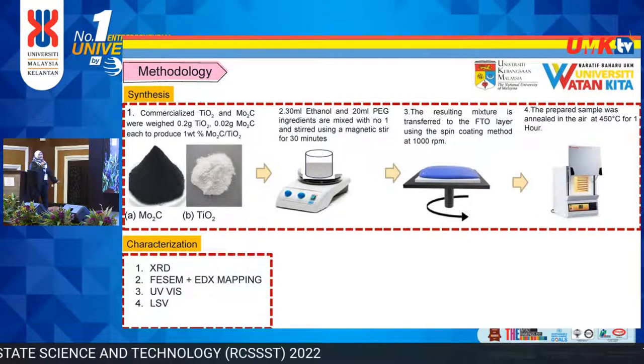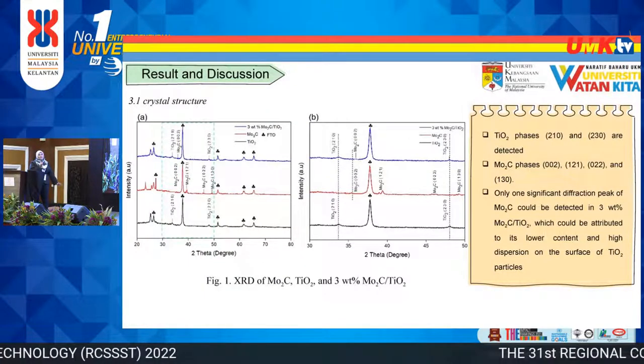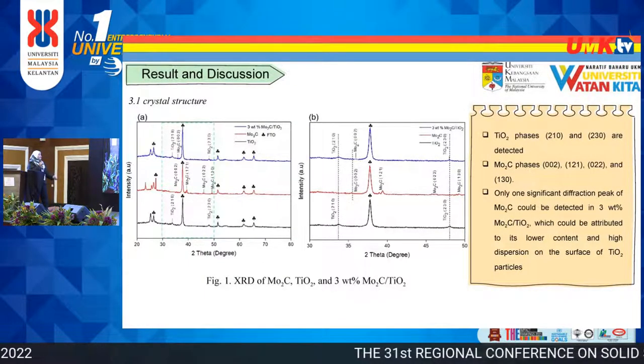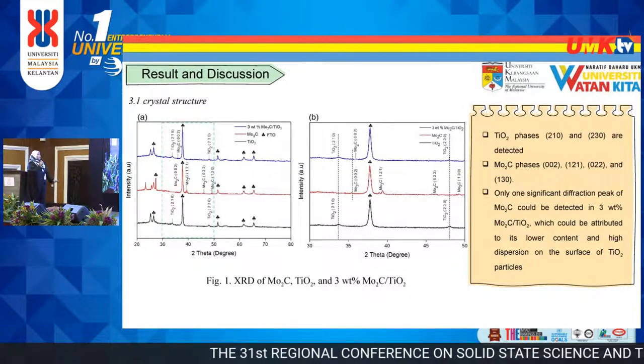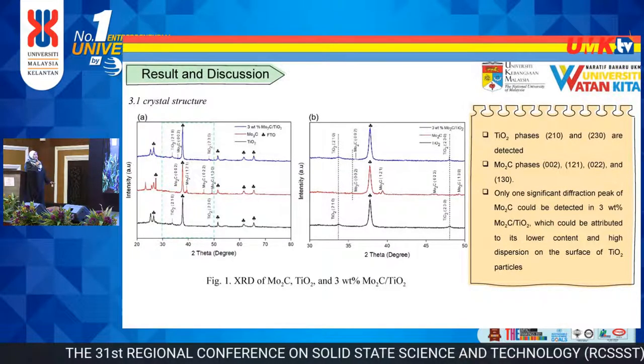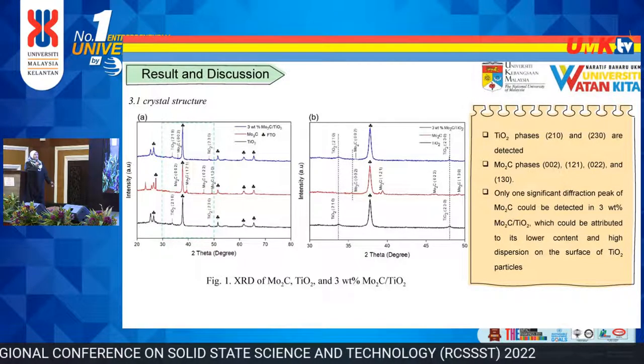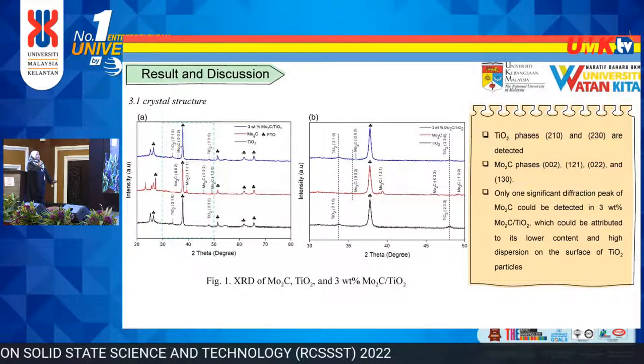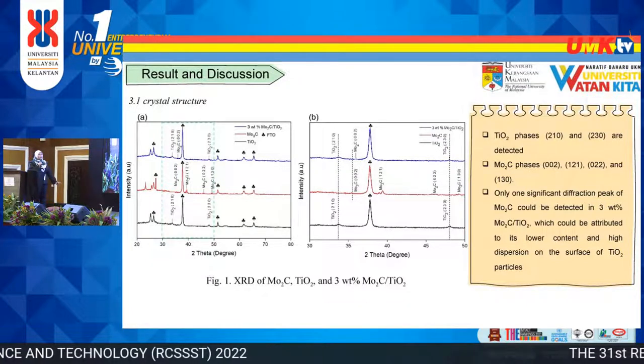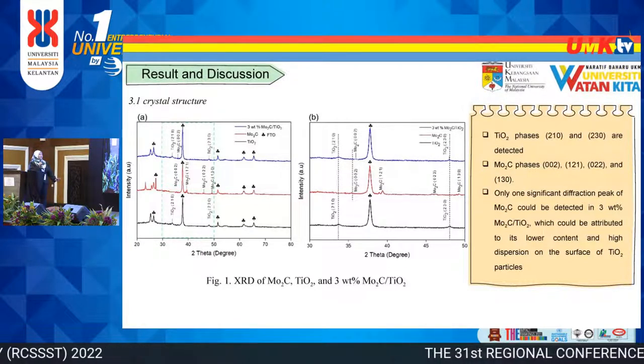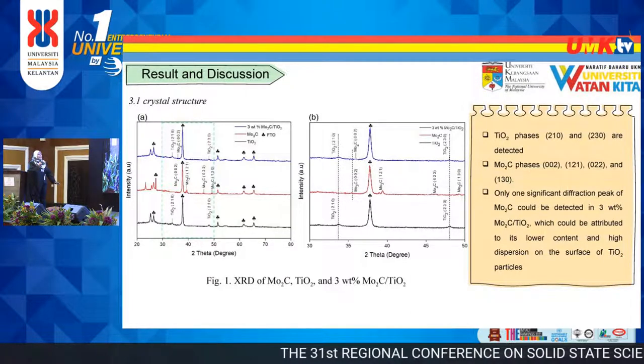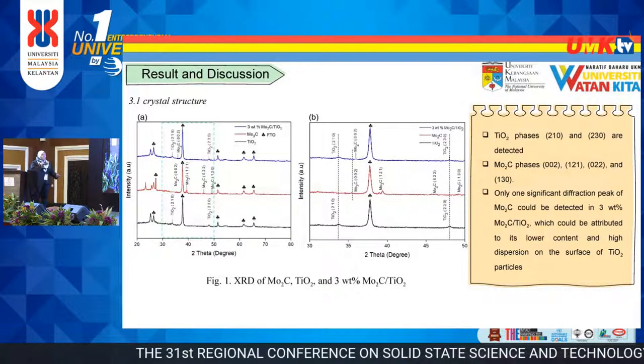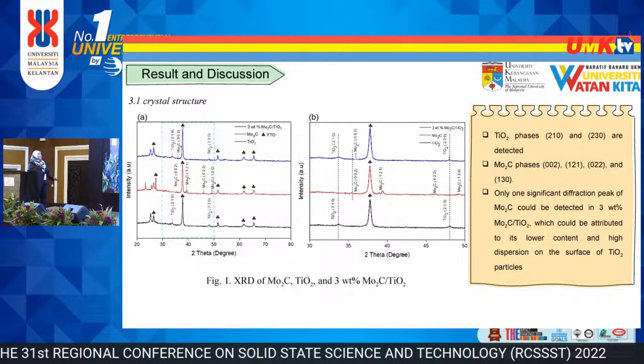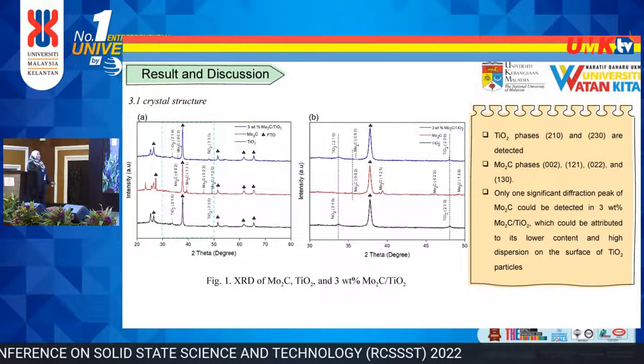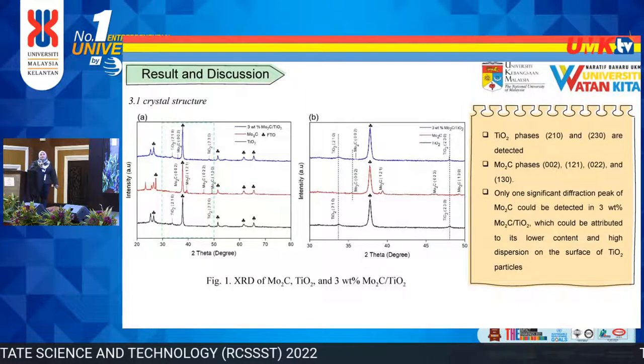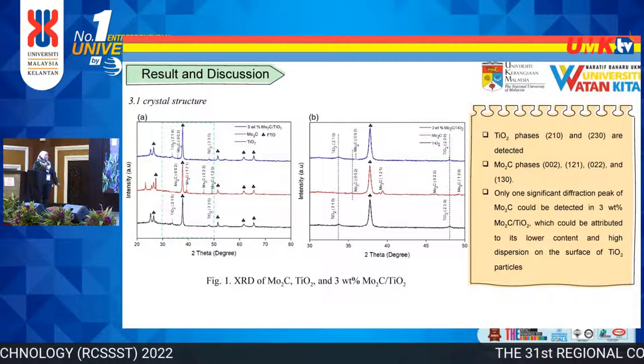Okay, next is this. I analyzed the crystal structure using XRD. As we can see from figure 1A, TiO2 shows the phases of 210 and 230 are detected, while in molybdenum carbide, the phases of 002, 121, 022 and 130 are detected. When 3% weight of molybdenum carbide is composited with the TiO2, only one peak of molybdenum carbide is detected. That's because of the lower content of the molybdenum carbide.